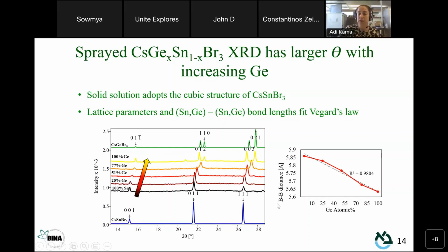We calculated the bond length, the B-to-B bond length. It's either tin-germanium to tin-germanium length, to see if it fits the linear law of Vegard, and we do see a good linear fit with regard to the concentrations. The concentrations are measured by ICP for the sprayed solution.